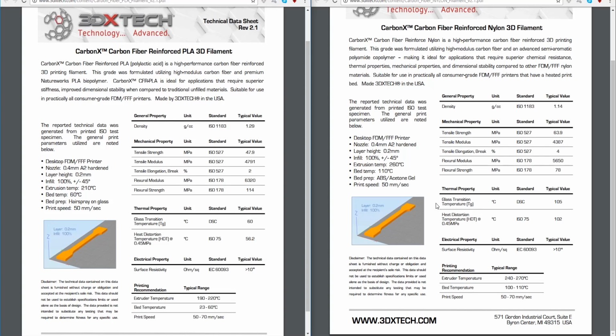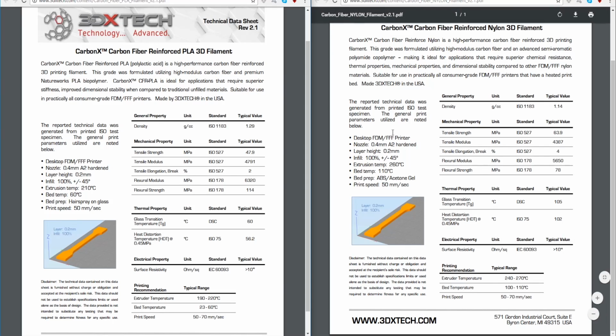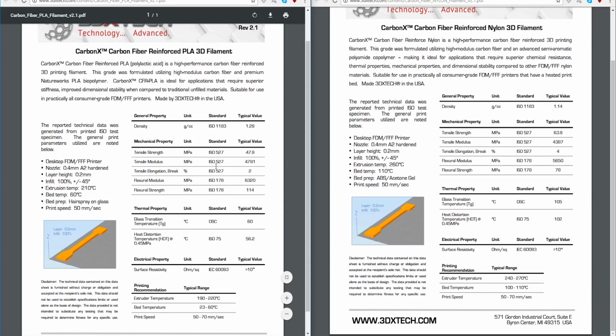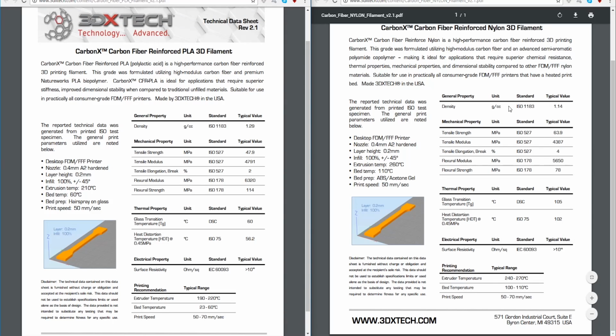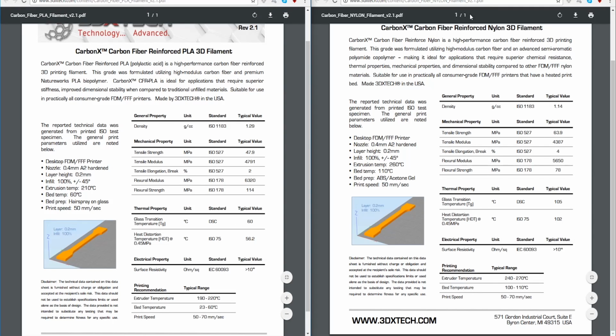So for the nylon, if you have a machine that has big stresses that would work for PLA too, and you want it to maintain under heat load, I would probably pick the nylon over the PLA. Except in flex. In flex you would probably want to pick the PLA. But if it was just a link holding something up, you would probably pick the nylon because it stretches even further. So yeah, for me, if I was using any sort of heat load, I would use this one. If I wasn't using a heat load, I would use this one. That's basically what it comes down to. So no heat, that's your pick.